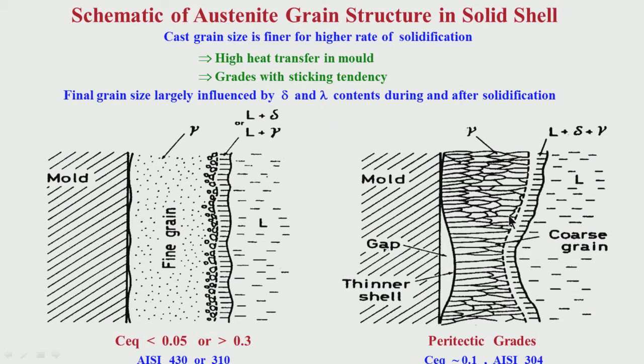So, here the grains are coarser because of heat transfer considerations, because of solidification characteristics. Here delta to gamma in the solid transformation is important. If you can start that delta to gamma transformation at higher temperature just after solidification, you do not allow the delta grains to remain at high temperature for quite some time, then you have relatively finer austenite grain size. Otherwise, if you have large austenite grains, then you have some difficulty.